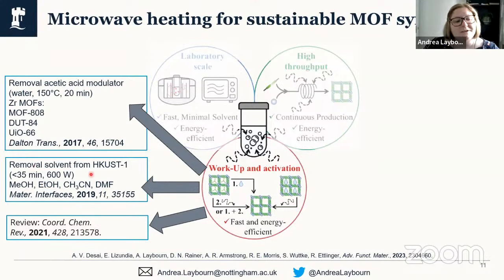And there's another report as well which has looked at the removal of solvent from HKUST-1. Now in this case, what the team had a look at was preparing HKUST-1, which gives a solvated structure, then saying, can we use microwaves to heat this structure and then evaporate out the solvent that is contained within that structure? And that's what they were able to demonstrate. So they could do this on the minutes timescale, between a few minutes up to 35 minutes, and for a range of different solvents, including methanol, ethanol, acetonitrile, and DMF. So essentially, they were able to heat the solvent contained within the pores and evaporate that out to give you a completely desolvated material, which you can then look at host-guest interactions and absorption from this.